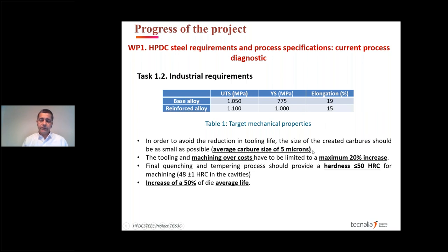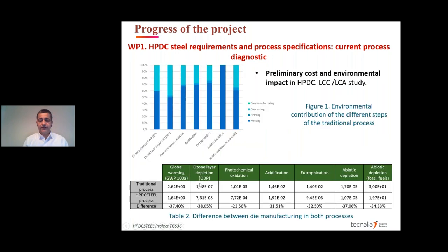So because of the previous works, we also know that we need a very small particle size of about 5 microns, and we also know that machining can have problems with the wearing of the tools and the reduction in the machining parameters. So we have a maximum of 20% increase in the price of the machining and die costs in order to try to make a material that can be employed in the market. So we have also an objective of about 50% increase of the life of the die.